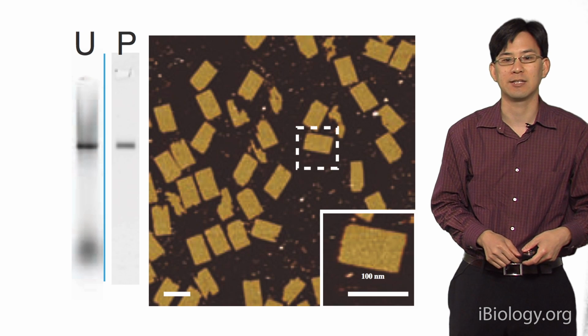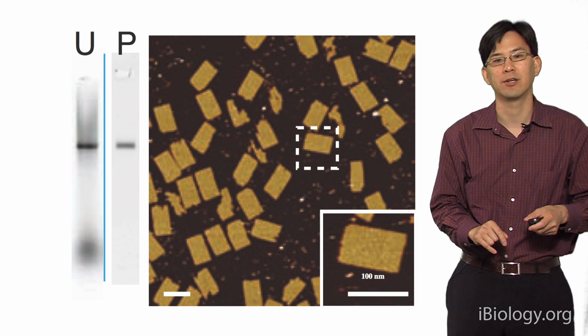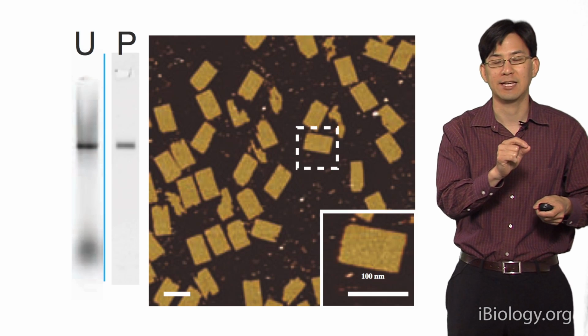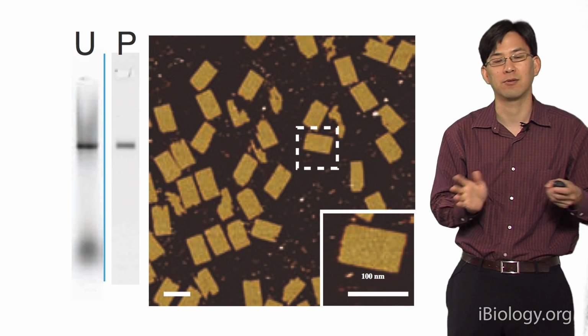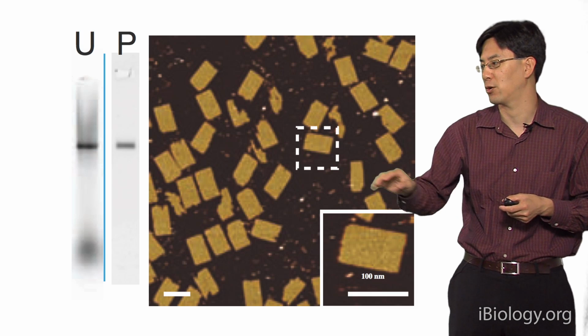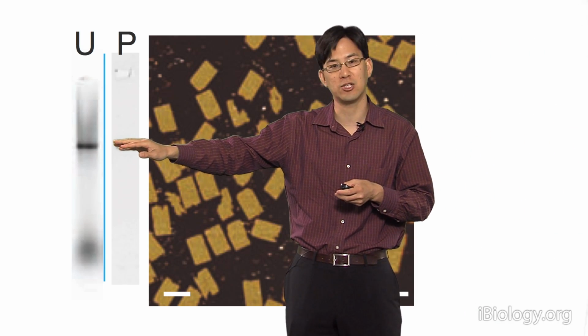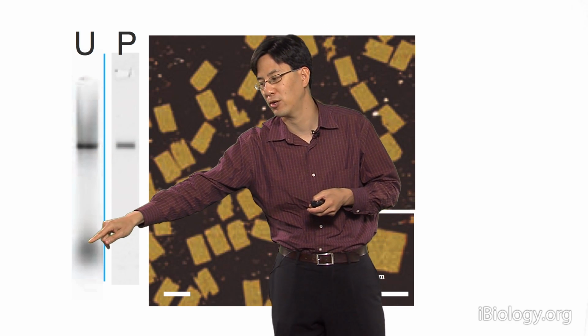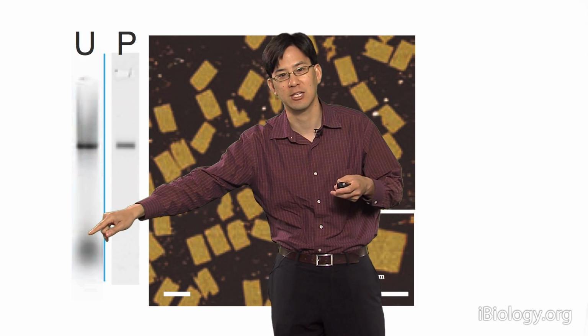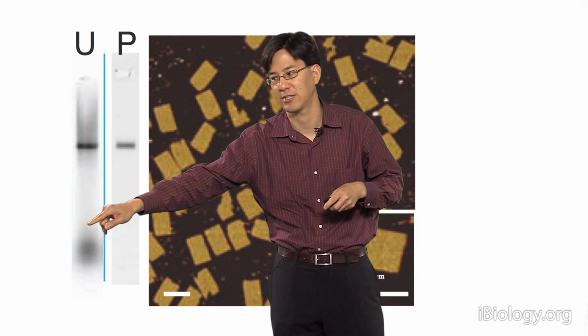So here what they've done is they've self-assembled a structure with something on the order of a few hundred unique tiles, each one with a stereotyped design position within the tapestry, and they found that they could make these in fairly high yield. So on the left we can see an agarose gel where we can monitor roughly the formation of the object. U means unpurified. And we have the initial building blocks on the bottom. You just cook these for a while. Again, you do this annealing profile where you heat to 65 degrees and cool to room temperature over the course of a day or so.